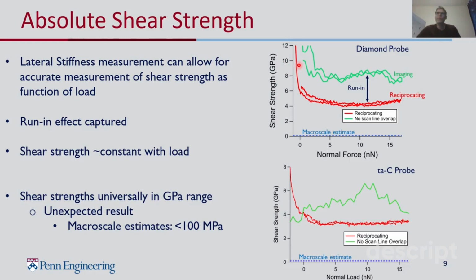And another way to quantify that is that macroscale sliding experiments, certain ones, can actually provide estimates of what the shear strength is in macroscale sliding with diamond-like carbons, including silicon oxide-doped diamond-like carbons like the material I'm studying here. And whenever that has been done, universally they find shear strengths below 100 megapascals. So that's orders of magnitude below what we see, and intuitively that's what you would expect, given that we know that diamond-like carbon materials are good low-friction materials in macroscale sliding. So there's a disconnect here. Something very different is happening in these nanoscale experiments than what ends up happening in the macroscale experiments.